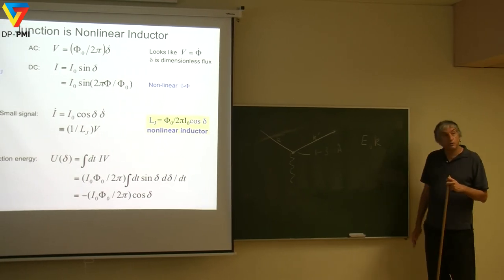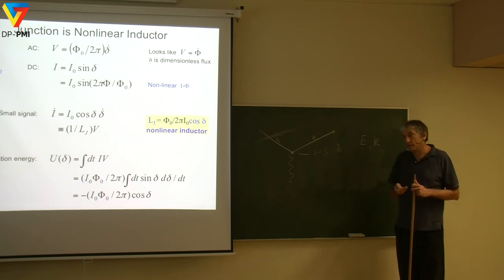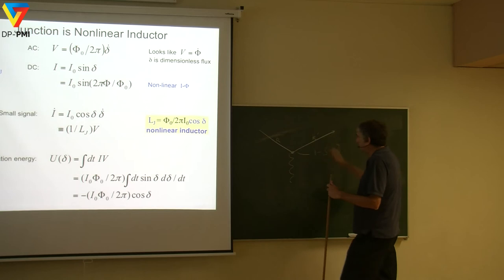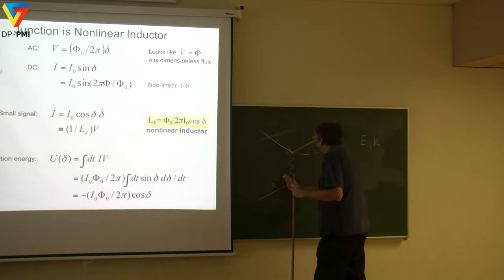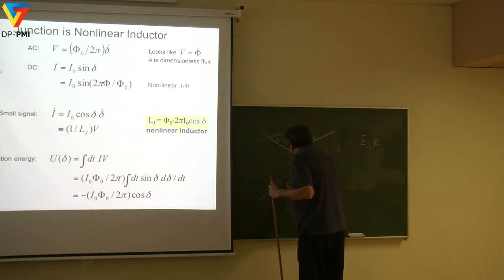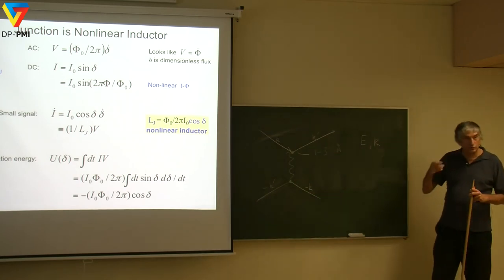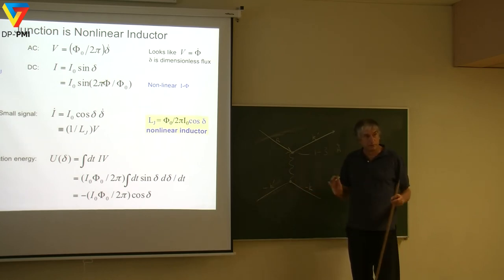Okay. So what happens is, because this process is really, really strong, it means that there's a second order process that can come in that turns out is pretty strong too, okay? And the process is this scatters K to K prime. We're going to have another process where you come in with K prime, and let's see, this scatters this way. Let me try to get this right. That you're going to have a scattering process that comes in here at minus K and scatters out at minus K prime. Okay? And it's second order, so you go to second order perturbation theory. But because this is so strong, the net effect here is actually pretty strong.